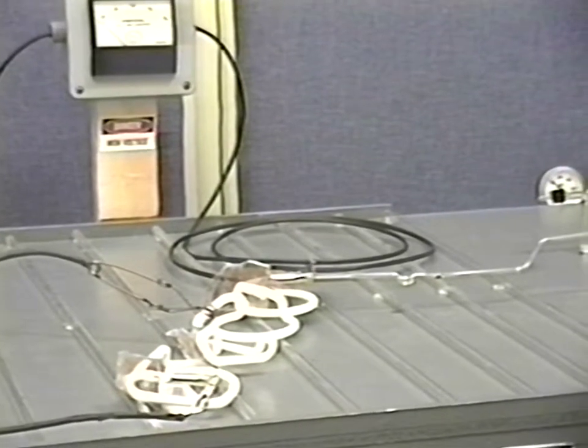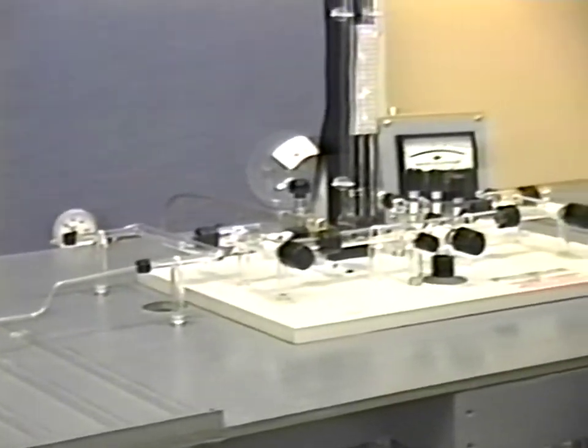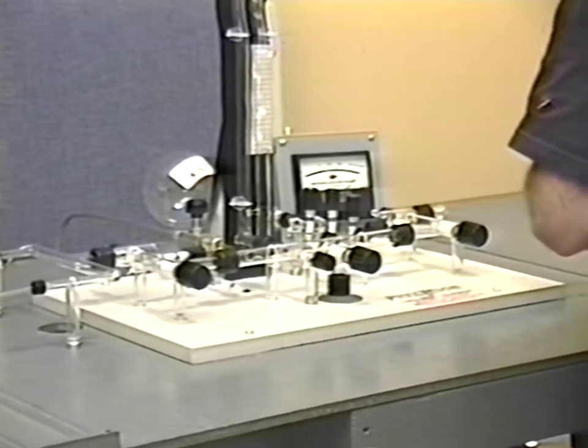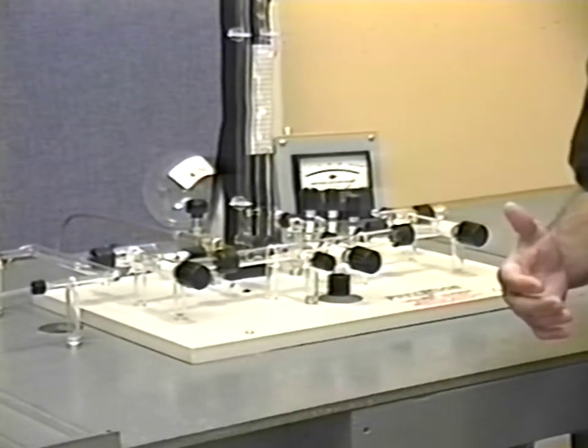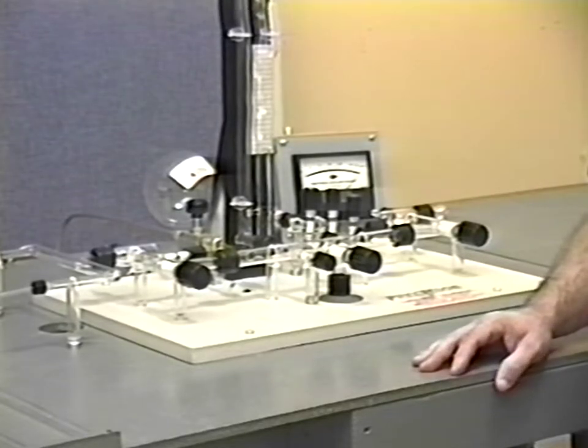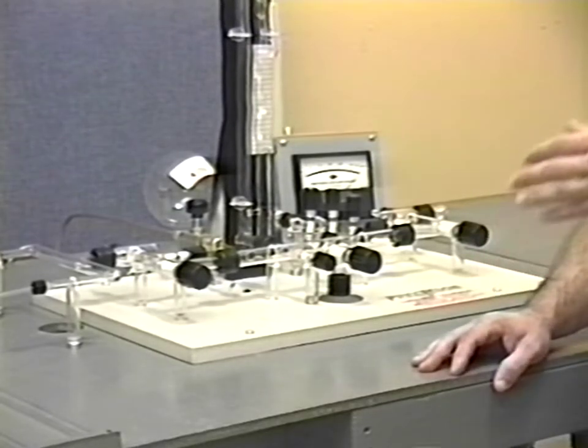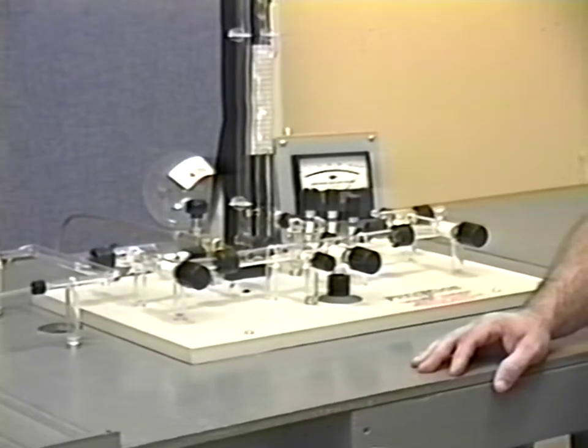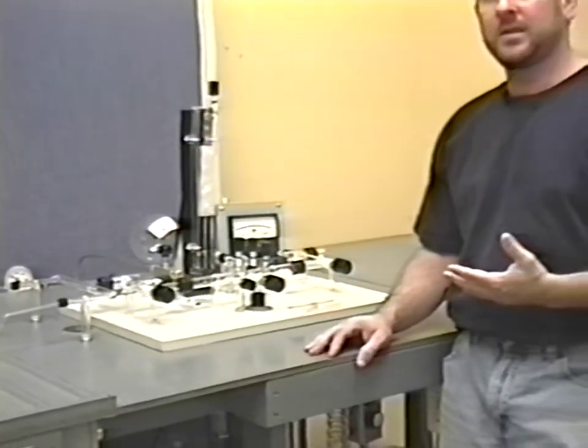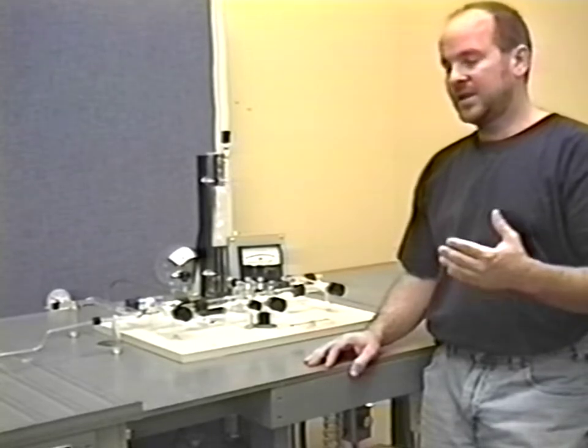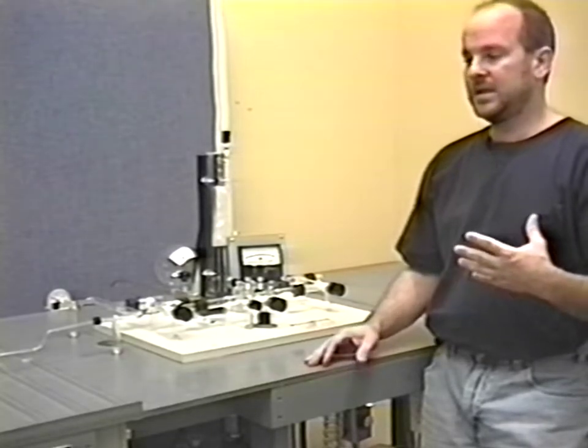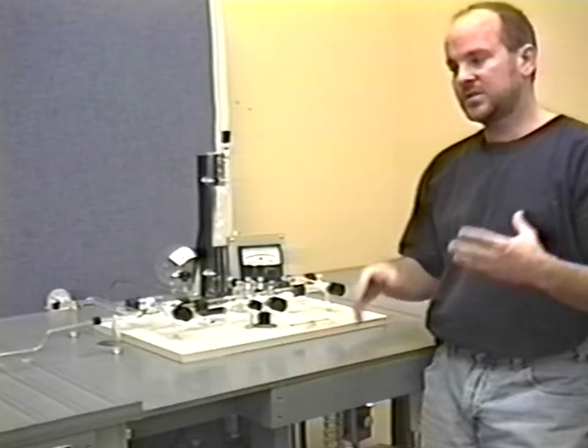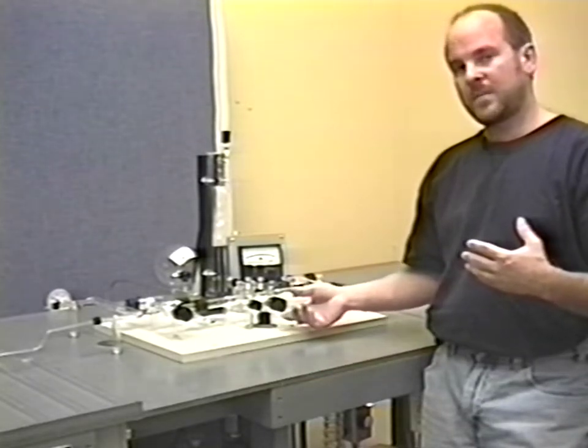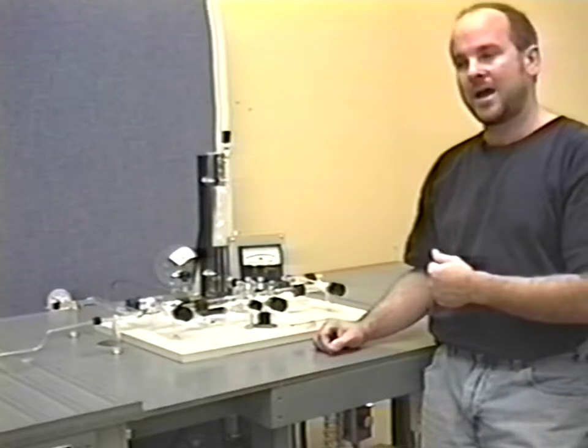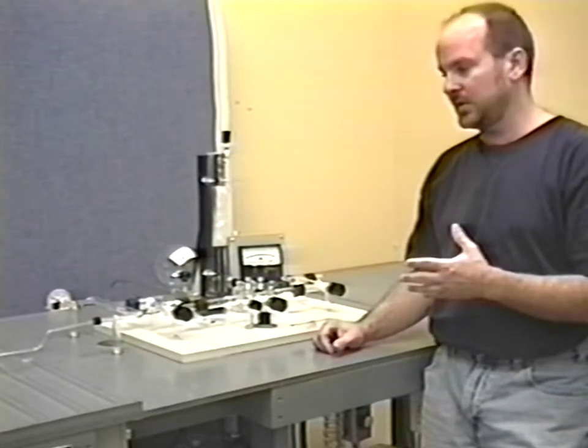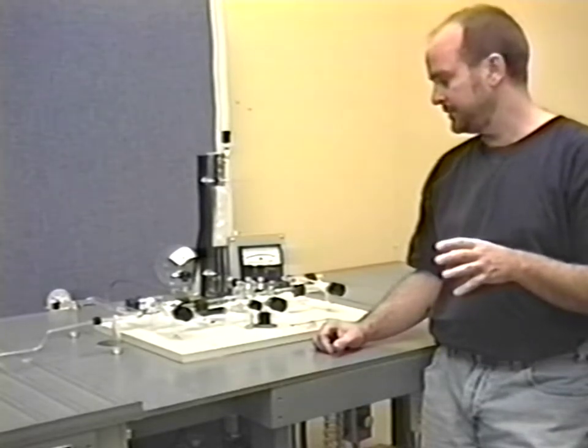Now that everything's all set up, I'm going to go ahead and start the processing procedure. What this is all about is I'm going to pull a vacuum into the system, heat up my unit several times, getting hotter each time until my electrodes are a cherry red and my glass is very, very hot. I do this because at that point, any contaminant that might be existing within my system is going to be released into suspension. I'll open up my main stopcock, the vacuum's going to suck it all out. We'll get all of the impurities out of our glass so we don't have any spotting or discoloration or darkening.